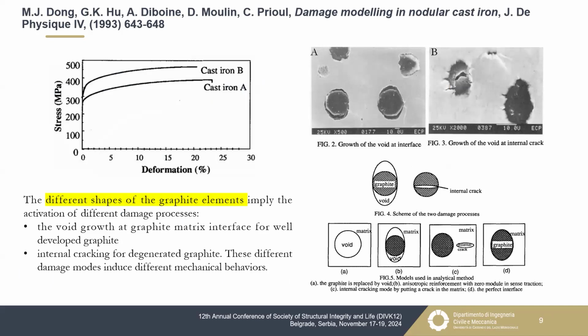For example, we have a paper where the role of the shape of these nodules was investigated, and considering tensile tests, they found that the damage mechanisms were different mainly according to the shape of these nodules. Perfect, almost perfect nodules were always damaged by means of debonding between the matrix and the nodules. Instead, degenerated, maybe that is too strong a word, anyway, not so well nodulized elements were usually cracked in the middle of the nodules.